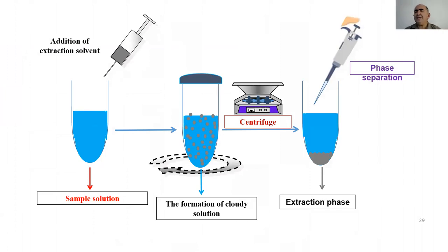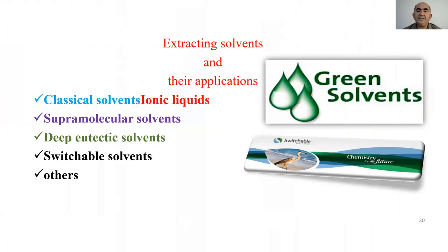This step is very simple. Generally, we can summarize it like this: addition of extracting solvents at microliter level to the sample solution, formation of a cloudy solution, then centrifugation, vortex, and other processes. We get two phases, and our extraction phase is only at microliter level. And after phase separation, we can easily determine our analytes in the extractant phase. In these works, we can use classical solvents, ionic liquids, supramolecular solvents, deep eutectic solvents, switchable solvents, and others.